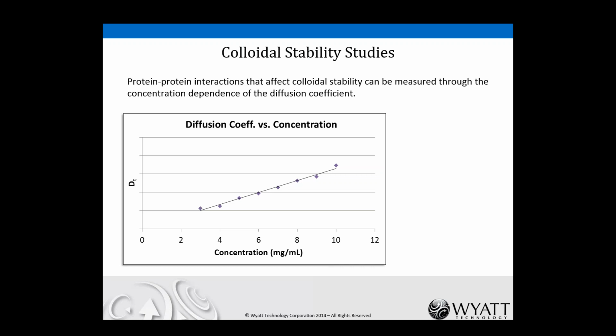And the way that we assess it is by looking at the change in diffusion coefficient as a function of concentration. So if the diffusion coefficient decreases at increasing concentration, that tells us that larger particulates are forming, and therefore there's a self-association. If the diffusion coefficient increases with concentration, which is shown in the graph here, that indicates that the molecules tend to repel each other and that they're nicely stable in solution.